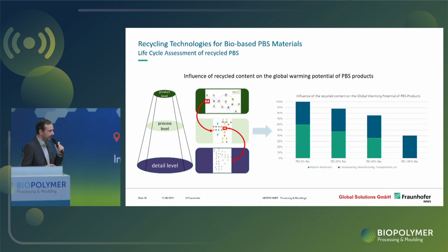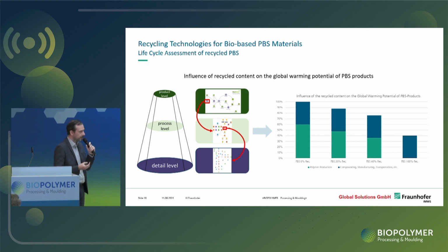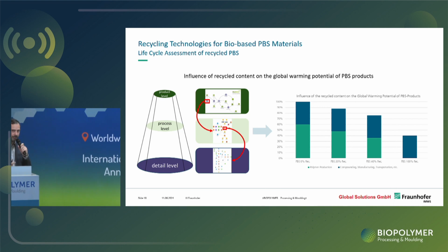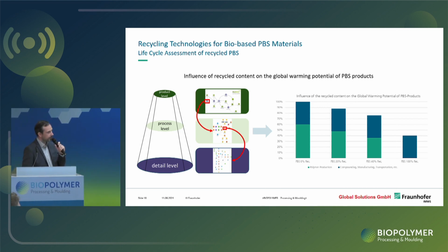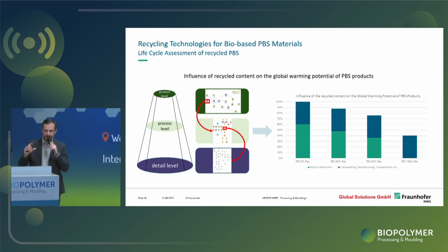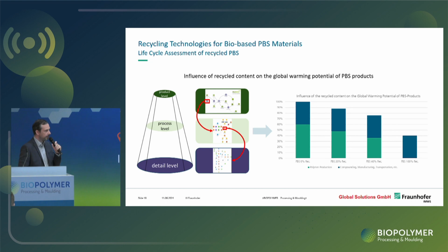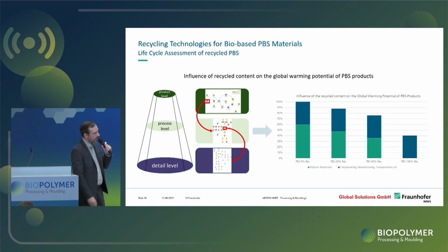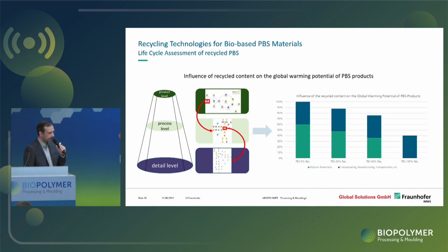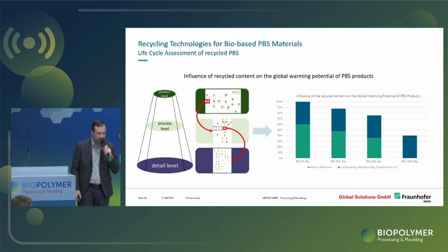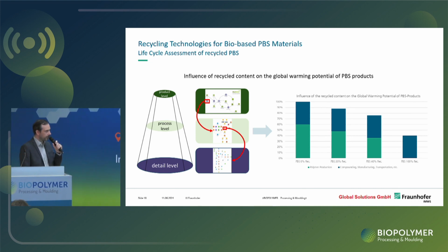Once you have the polymer in hand, 60% of the carbon footprint of this material comes from the fermentation, the polymerization, and so on. The rest is produced through processing to a certain product, transportation and so on. So if you use recycled material, you do not have this 60% again in your material, and the more recycled material you put into your compound, the lower your carbon footprint. Here you can see some numbers. With 20% of recycled material, you get already a significant reduction, and if you use 50% or even more, you can see that the carbon footprint of your material goes significantly down.